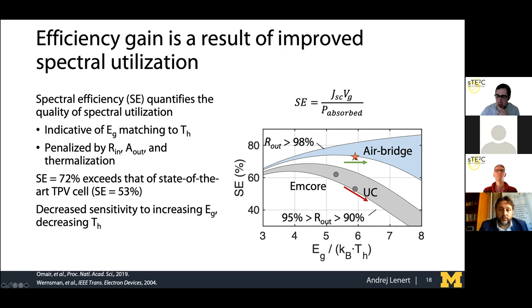The AirBridge architecture is different from previous architectures because it opens up the possibility of working in a regime where we're not very sensitive to the band gap of the device or the temperature of the heat source. That's this blue regime here. Whereas in the past, when we were limited by out-of-band reflectance of 95%, we were on a trajectory where if we increased band gap, we would get much lower efficiencies. And the other way to think about this is that if we decrease temperature, we would get much lower efficiencies.